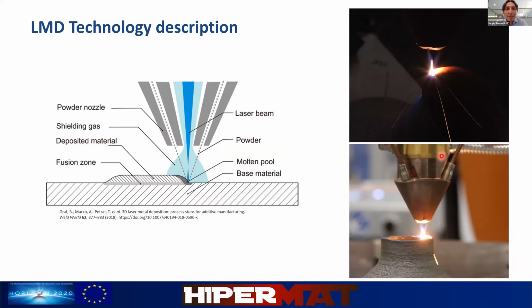Okay, let's see now in more detail what's going on during the process. We see that the powder, that is this dashed line, meets at a point, and at this point, the laser in dark blue meets the powder, and a melt pool appears. There is also a shielding gas in light blue that protects the melt pool from oxidation.